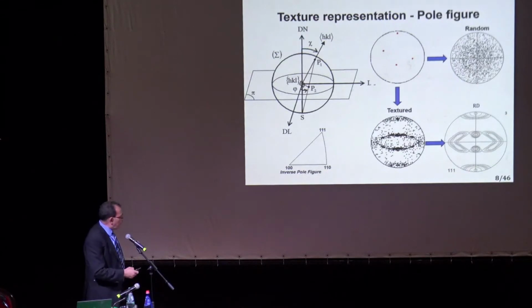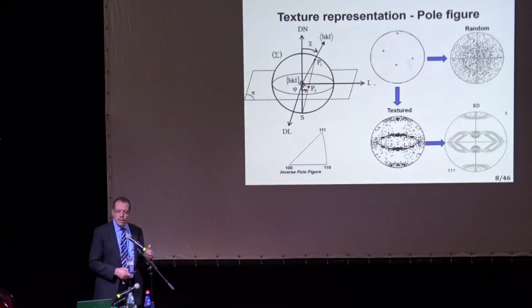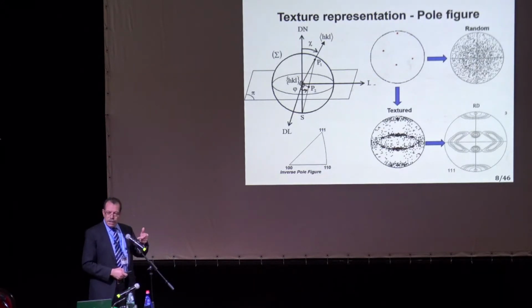The other way of representing is if you have any axial loading, like compression or tension, we use what we call inverse pole figure. In fact, we sit in the crystal axis and we see how the macro axes rotate. So you plot the 100 and 111 for the FCC metals or FCC materials in general, and then if you do a tensile test, you may have dots here, and each dot will represent where the tensile axis sits with respect to these 3 directions.